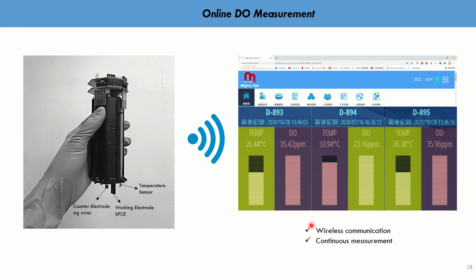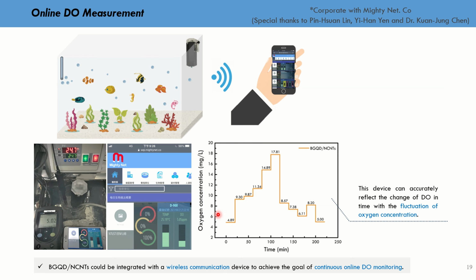Then we applied this electrocatalyst in a commercial dissolved oxygen sensor. After connecting to Wi-Fi, the dissolved oxygen measurement data will be uploaded to a web page. This wireless communication and continuous measurement can effectively reduce the need for human resources. At last, the dissolved oxygen measurements by the commercial electrocatalyst and the BGQD/NCNT electrocatalyst were compared. The results show that the measurements from these two materials are similar. Moreover, BGQD/NCNT can detect dissolved oxygen precisely in a floating environment, indicating that this material can successfully be applied in wireless communication and be helpful for the development of aquaculture.